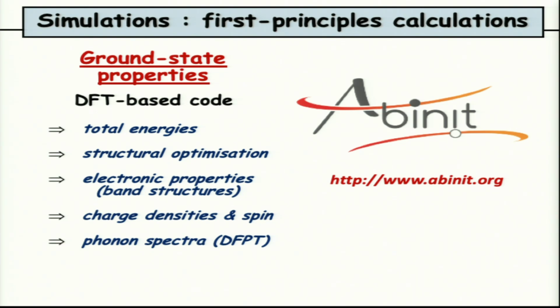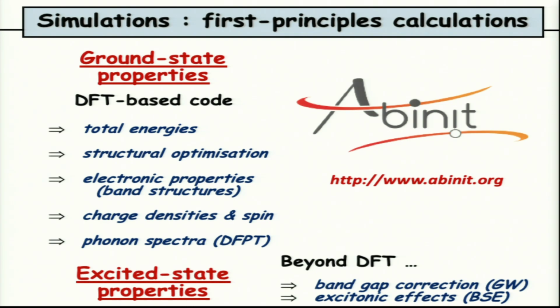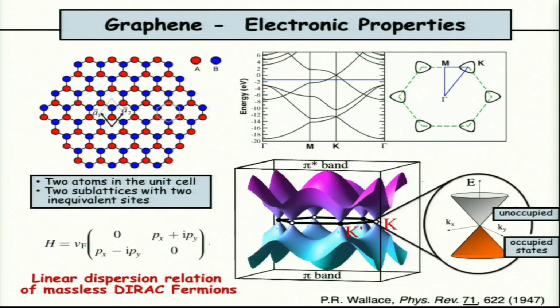We have access to electronic properties, to charge density and spin, and also when we go to density functional perturbation theory, we can have access also to the vibration of the atoms in the solid, so with the phonon spectra. It allows also to go beyond DFT when we investigate excited states, for example, and mainly we can have band gap correction, because with DFT there is a clear problem in the prediction of band gaps, so you have to correct them, and also if you want to have access to excitonic effect, you have to solve the Bethe-Salpeter equation. But this is not the main part of the talk here.